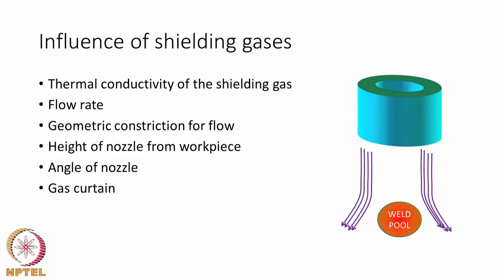The geometrical construction for flow also plays a role. If there is no geometrical construction, that means the gas is flowing freely and expanding as it goes away from the weld pool, then its velocity drops, and that determines the rate of heat loss from the weld pool to the environment. In case it is constricted, then the velocity of the gas going through the nozzle will be higher, and that means that the heat loss will be slightly higher than in the previous case. So, whether a geometrical construction is there or not is information that we need to know.